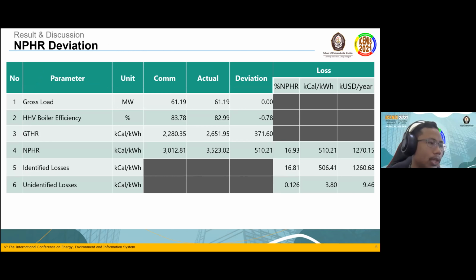This table shows the actual performance test result compared to the commissioning. There was no significant difference in coal quality used between the actual and commissioning performance tests, around 4,200 kilocalorie per kilogram. The result of the actual performance test at 61 megawatt gross load obtained a heat rate value of 3,523 kilocalorie per kilowatt hour, while the commissioning result obtained a heat rate of 3,012 kilocalorie per kilowatt hour at the same load.